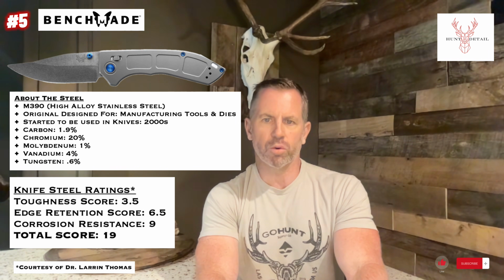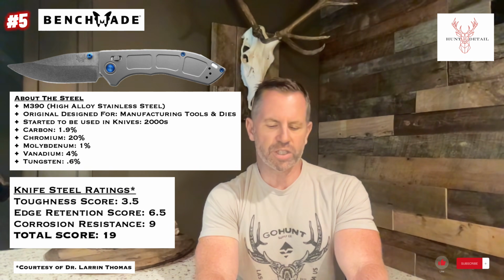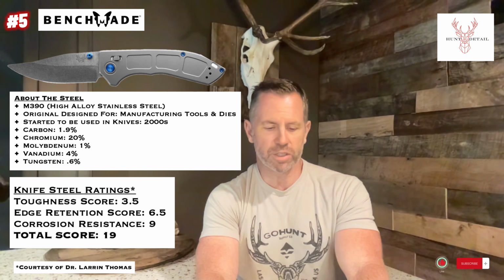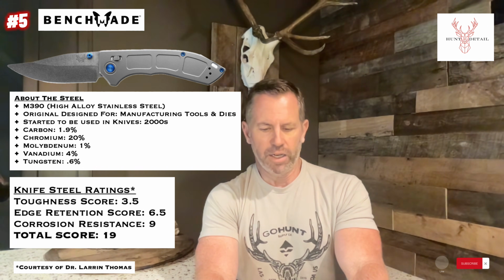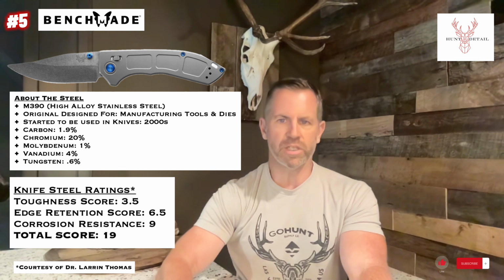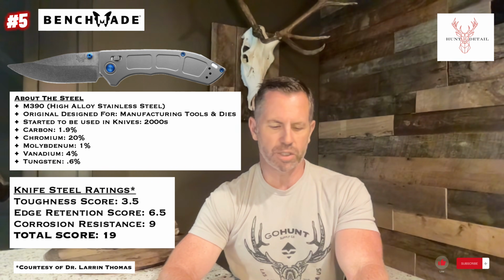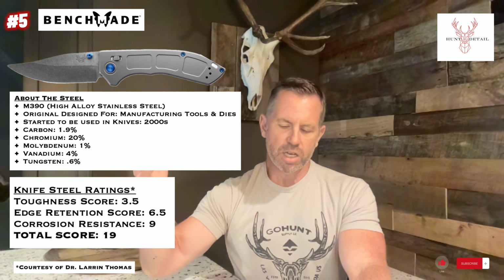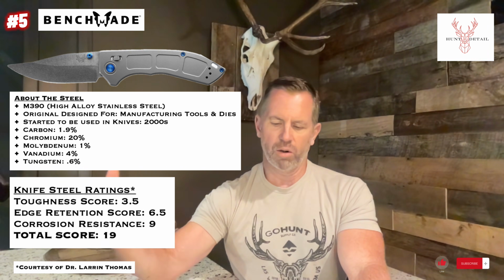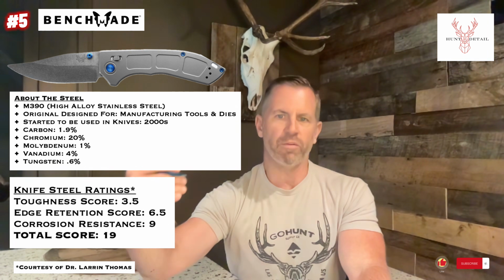And so from a toughness standpoint, it scores 3.5. From edge retention, it scores a 6.5. And from corrosion resistance, it scores a 9. And that's the highest that we've seen from a stainless steel knife from a corrosion resistance so far. And obviously you see that play out as a function of that high chromium level.